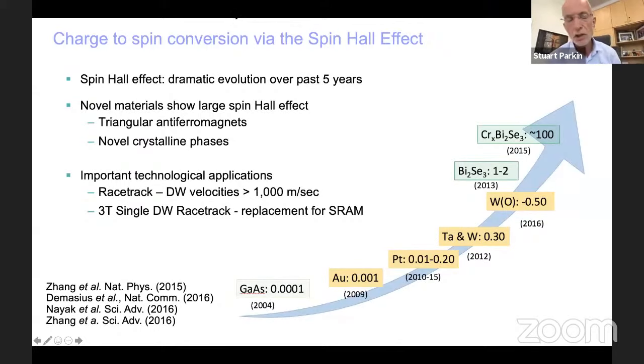We've shown, for example, that chiral antiferromagnetic materials themselves give rise to a significant intrinsic spin Hall effect related to the chiral antiferromagnetic structure. We demonstrated this in manganese 3 iridium, but you could also anticipate large spin Hall effects in certain topological insulators and topological metals.